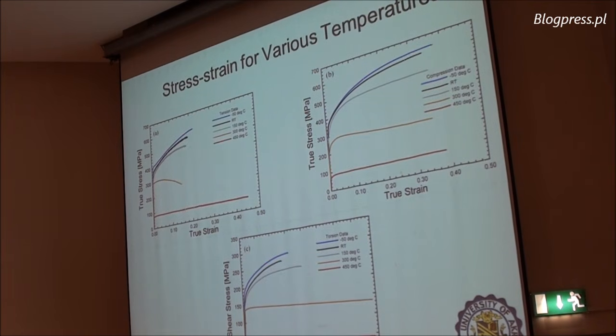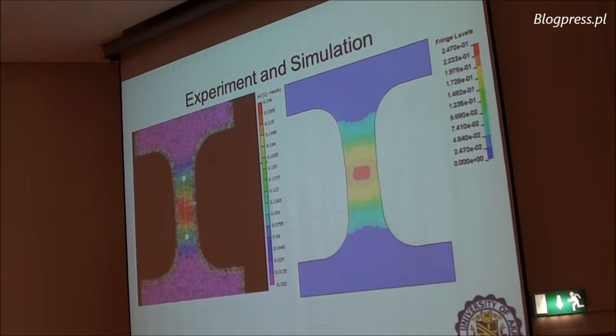Now also, for the same strain rate but at room temperature or low temperature especially, the low temperature is the blue, minus 50C, which is the cruise temperature of the airplane at 30,000 feet. Compared to room temperature, you can see that again the colder the material is, the stronger it is, and still not losing any of the strength.